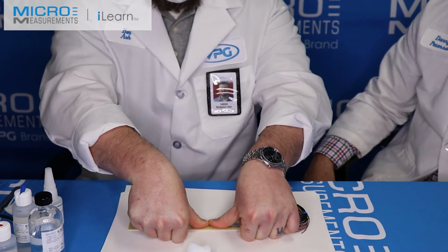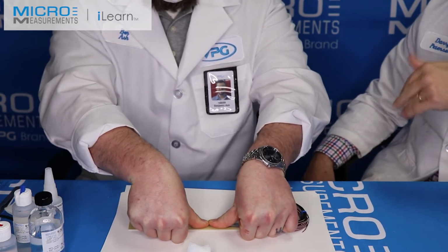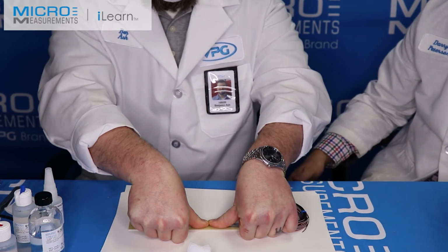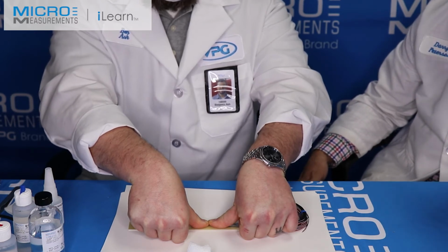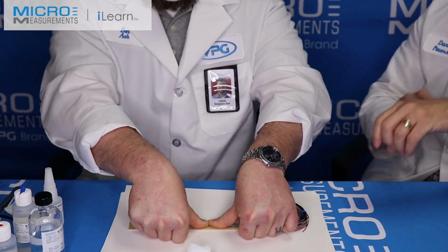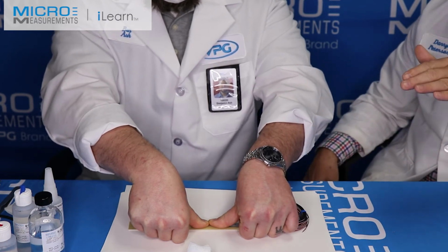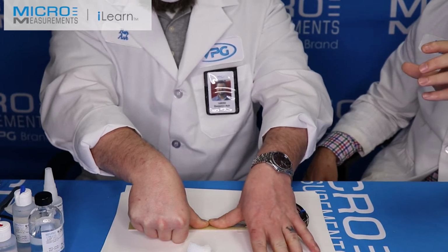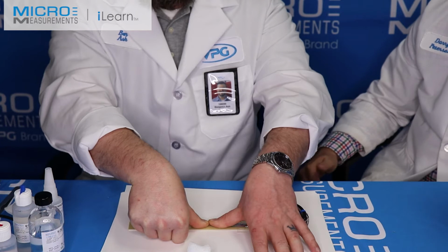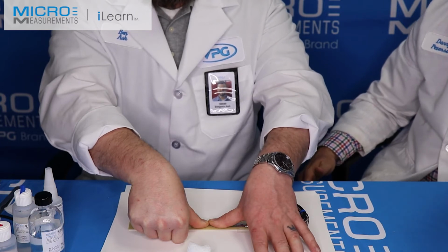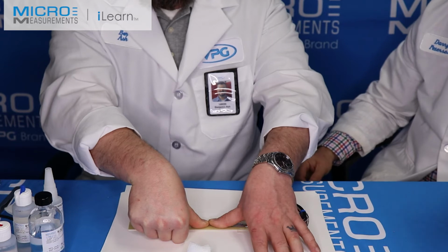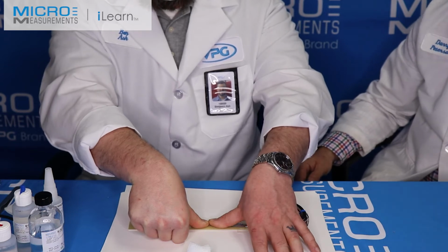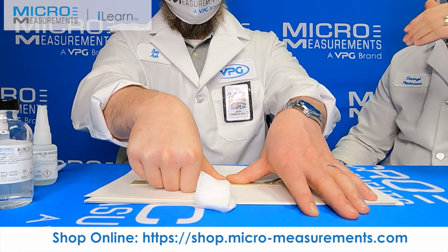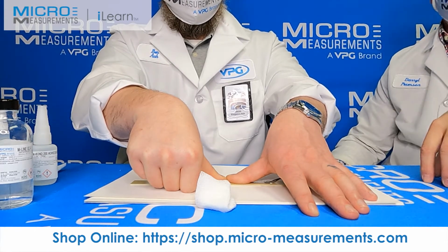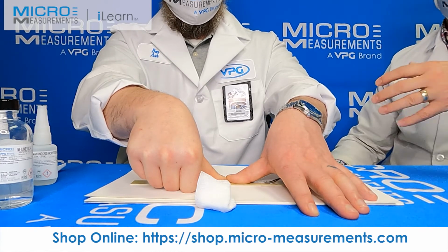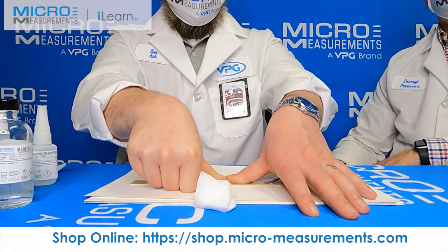That's the great thing about using MBond 200, is that once you apply it and once you give it 1 minute of pressure, that's all the curing really that's needed. Now we normally recommend that after the 1 minute of pressure, you let it sit for another 2 minutes, and then you're ready to remove the tape. The key point to recognize, though, is after that 2 minutes, the installation, other than the environmental coating, is basically done. So you're basically ready to start testing. You could brush on some environmental coating, give that a few minutes to sit, and then you're ready to start running your test. But this beam and this adhesive and this gauge, they're ready to start reading strain as soon as you finish that 2 minute period of time to let it sit.